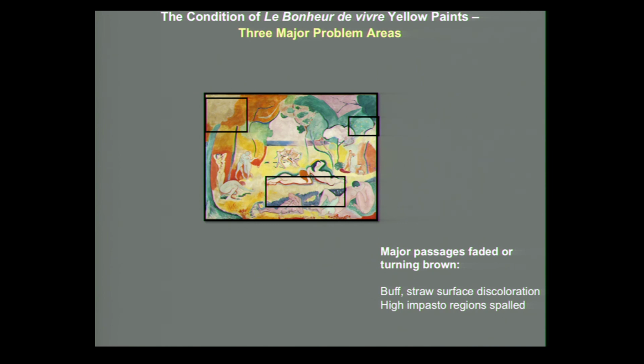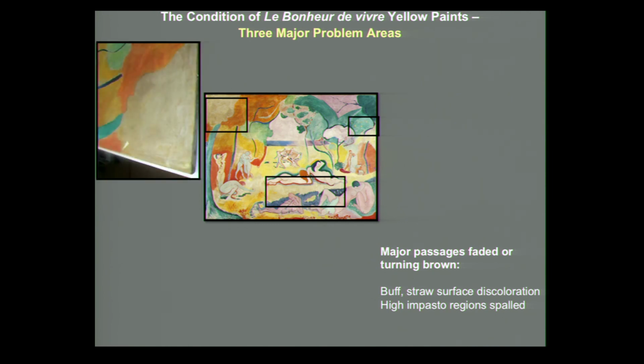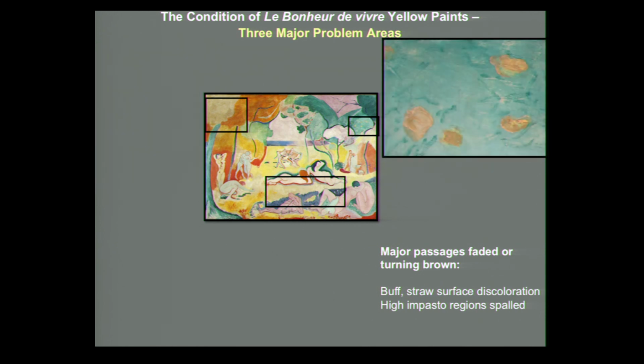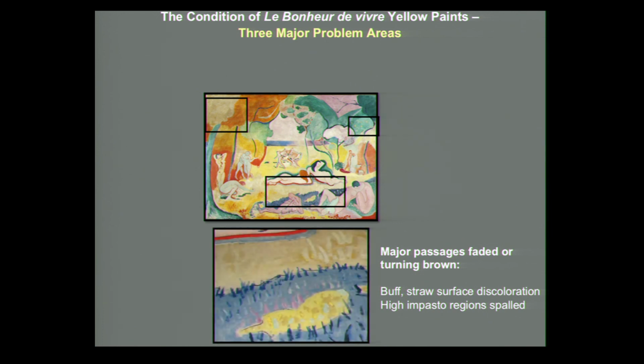So if we look at the condition of The Joy of Life, there's 3 major problem areas. There's the area that's turning brown in the upper left corner, and then there's this kind of tan film that's forming on top of the fruits in the tree. And then there's the ivory color forming underneath the central reclining figures as the yellow fades away. And we're seeing that the high impasto areas are flaking away.